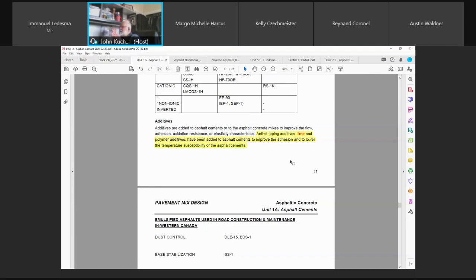That's quite common when you're going to use recycled asphalts and blend them with virgin asphalts. You'll have a virgin mix, then take recycled pavements that have been ground down, heat them up, and mix them, maybe 75-25 or 80-20. So now you're using recycled pavements. The asphalt cements in these recycled pavements are old, aged, and hardened.